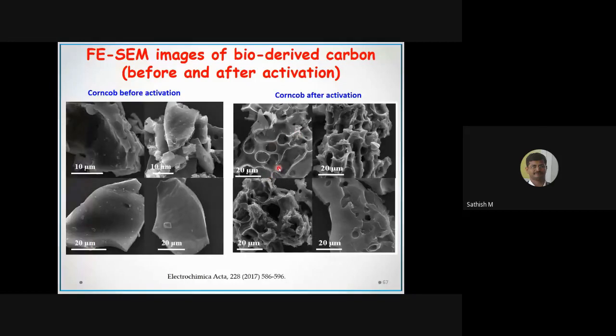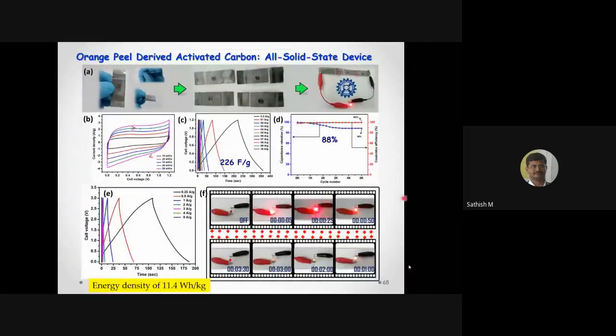You can see it creates a lot of holes or porosity. Because of these pores, the surface area of the materials will be very high. So the ions, the electrolyte, can easily penetrate through these pores. So these materials could be effectively used for any application, even lithium-ion batteries or supercapacitors. In this case we used it for supercapacitor applications.